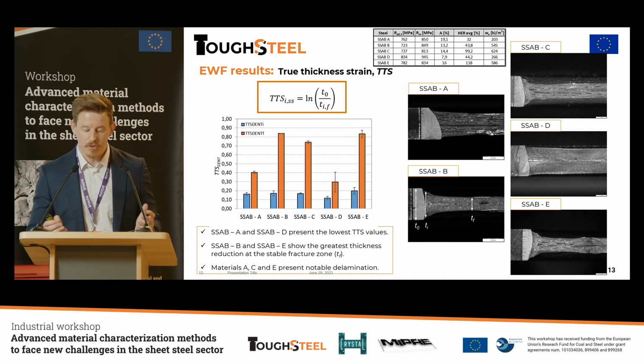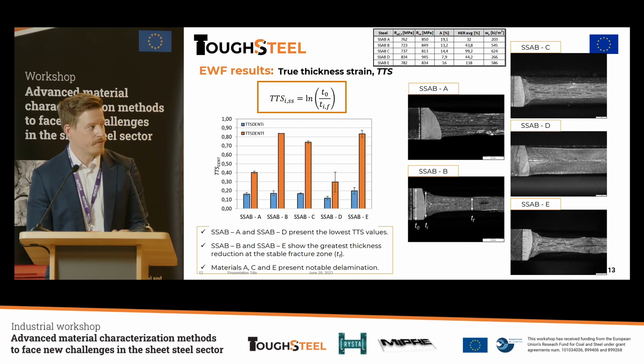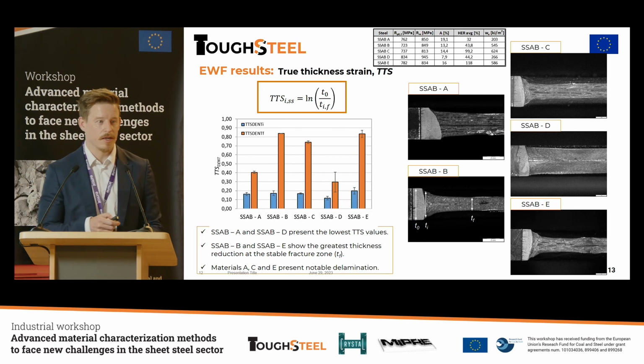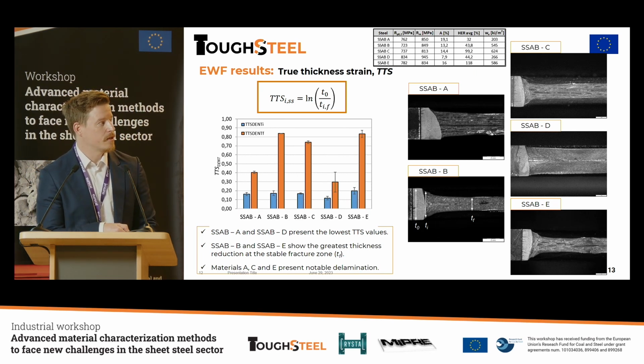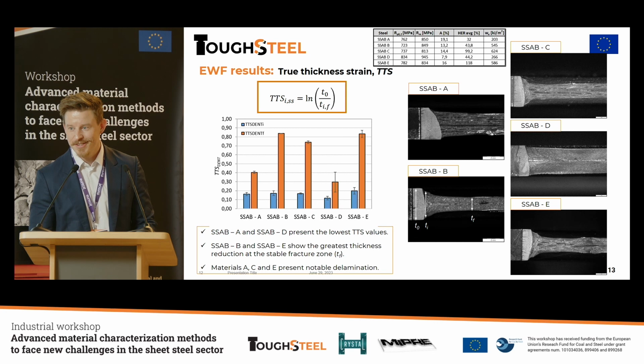And one thing that I want to highlight here is, if you are looking at the fracture surfaces, now I'm using the laser only, most likely not visible in Teams, but steel A, we can see severe delamination, steel C, the same story, and steel E, quite a severe delamination. But it doesn't seem to affect fracture toughness or these true thickness strains, because steel A is on a really low level in both, but the other 2 laminated are on a really high level of results. And again, something maybe we don't fully understand yet.